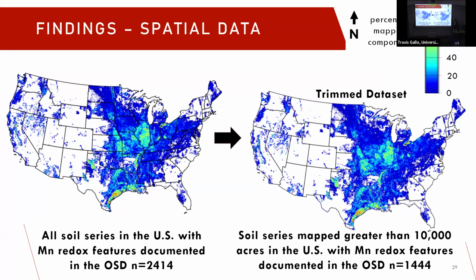The white areas of these maps show you where no manganese features are mapped. The blue areas show you where up to 15% of the components of soil series may have manganese described within the OSDs. And then the teal and turquoise areas show 30 to 50% where series may be mapped as components with manganese redox features. And then there are a few isolated red pockets where it's 80 to 100% of the components mapped that had manganese described within the OSD. This is along the Gulf of Mexico coast, between Houston and Corpus Christi, up nearby Toledo, Ohio, and then nearby Champaign, Illinois.